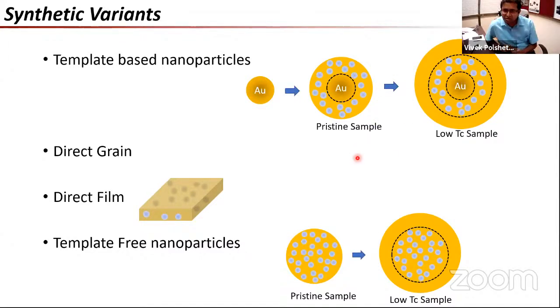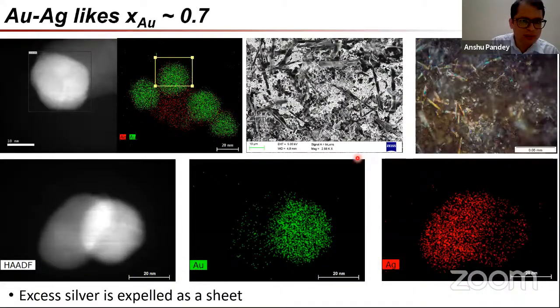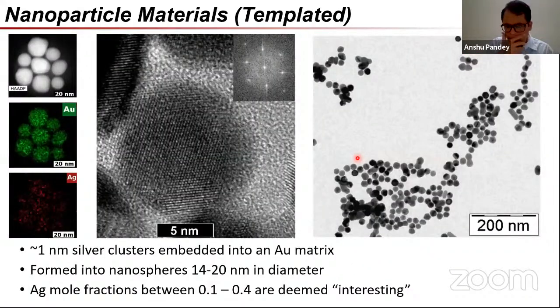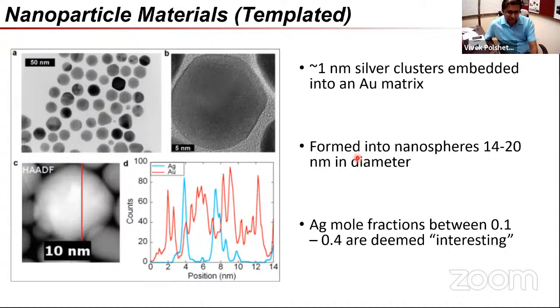Anshu, I have one query on your EDX line map. Sure. Sorry, where did it go? Yeah. If one assumes that the silver nanoparticles are also on the surface of the gold, rather than inside, they can also be on the outside. And if I do a line map, I will get a similar line map again. You would get a very similar line map.